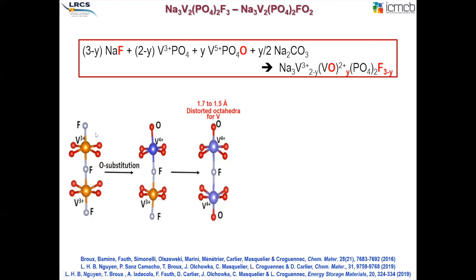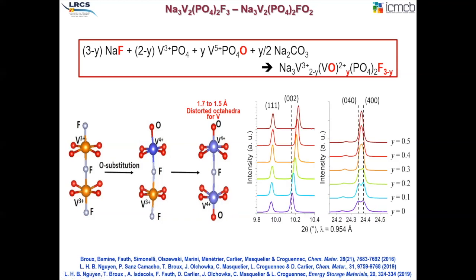Because oxygen actually substitutes fluorine in these crystallographic sites around vanadium, this creates shorter vanadium-oxygen bonds, on both sides of the two crystallographic sites for vanadium. So basically we can end up with a compound that has one fluorine and two oxygen around the vanadium. This is clearly seen from X-ray diffraction.